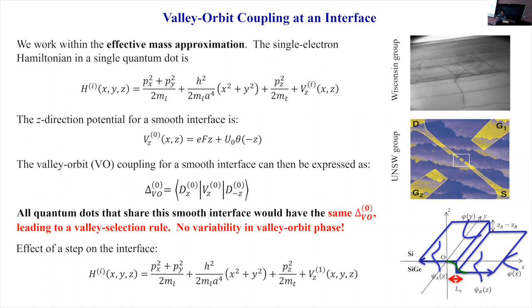In silicon germanium, because you grow the sample by MBE with very high quality, you can have a relatively flat interface, but generally you have these so-called steps, where you have silicon and silicon germanium, but then at some point you shift that interface by one atomic monolayer. Okay. This strategy was implemented mostly to release whatever strain is in the sample, so people tend to do that. And at the end, if you look at the interface, you see these different steps at the interface. Okay. So my student started to introduce one step, maybe two steps, and see how the valley-orbit coupling could be influenced by that.